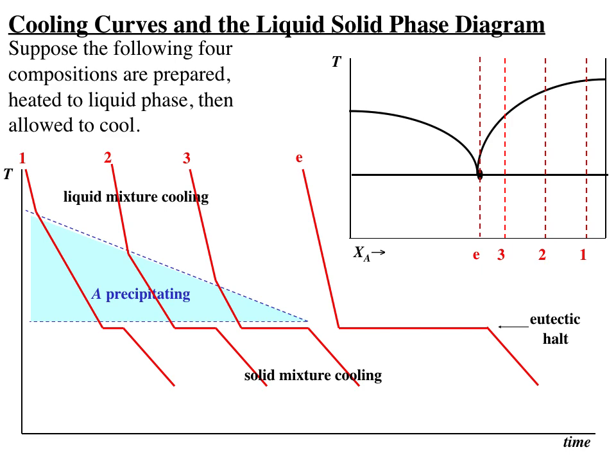Notice there's a shorter eutectic halt for composition 2 because there's less of the eutectic present when I finally make it to the eutectic point along that cooling curve. Then finally, I look at cooling curve 1, in which I have the most A present. So there's a discontinuity where the A begins to precipitate out. Notice A has to precipitate out the longest period of time before it reaches the eutectic amount of A present. There's the shortest eutectic halt for that particular curve because there's a minimum of that phase present, because of the massive amount of A that's already precipitated out. So the eutectic halt is shortest for that one.